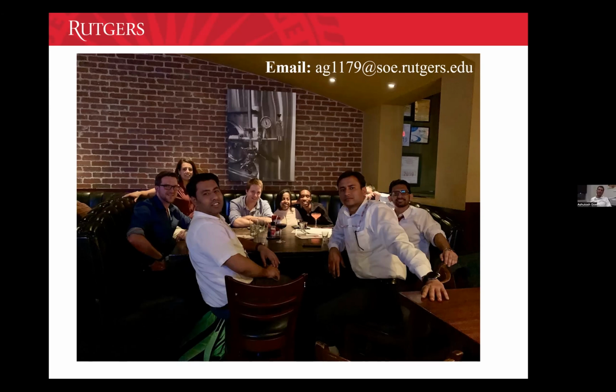Okay, so a normal glass, I'm assuming you're talking about, let's say, your container glass or your window glass, right? That's a pretty simple chemistry where you take sand and limestone and baking soda or washing soda, and you mix them in a proportion, and you heat them to around 1,600 degrees C, and you get a glass out of it. There's not much challenge to that. In this case, you're talking about almost half the periodic table going into it. So, making glass is not a problem.